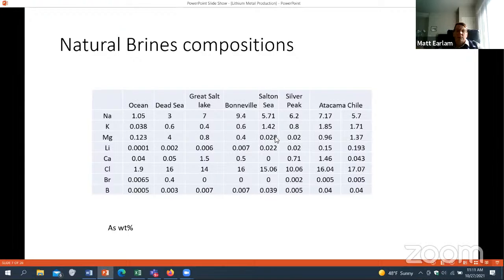There's also lithium in the Salton Sea, which has been subject of investigation to try to remove. And there's a company now that's trying to remove lithium from the Salton Sea. It's been tried before. It's difficult hydrometallurgically because there's a lot of arsenic in the Salton Sea. Makes it difficult to separate and handle the byproduct arsenic, which is a problem. Silver Peak is a brine deposit in Nevada, which is used right now for exploitation. And then you look at the brine deposits in Chile, and they're just so much higher in lithium than any of these other sources. And you can see why that would attract mining companies in their interest to extract lithium, because there's a lot less water to remove per lithium weight than there is on these other solutions.